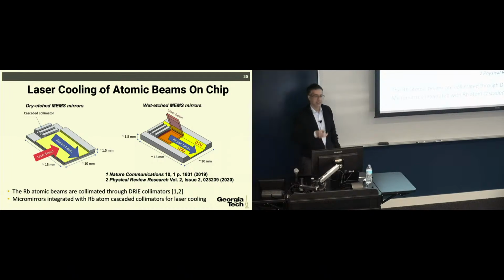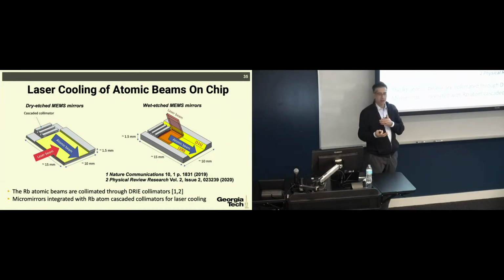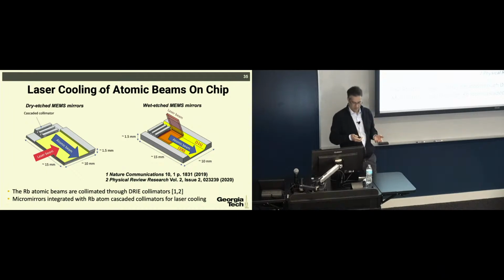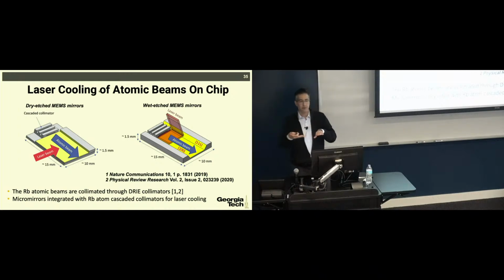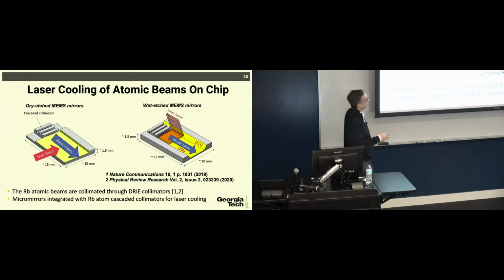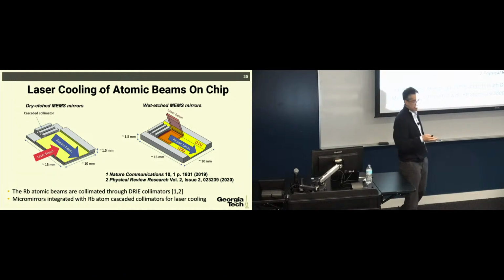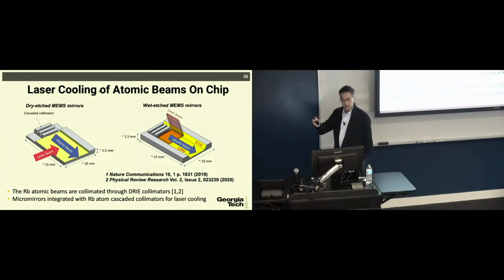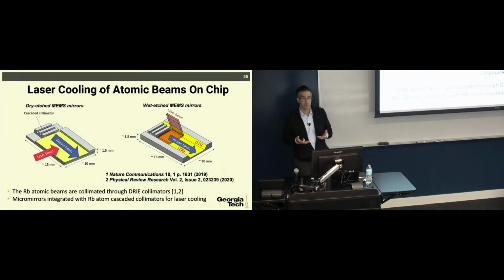On top of that, people are still interested in further collimating and cooling the atomic beam that is coming out of these collimators. They do that using laser beams. For laser beams, it's very hard to get the laser beam to be exactly at a 90-degree angle to the path of the atoms. So it is important to have mirrors integrated with these collimators that would deflect the light in a desirable direction, and just have it interact with the atoms and cool them via that interaction.